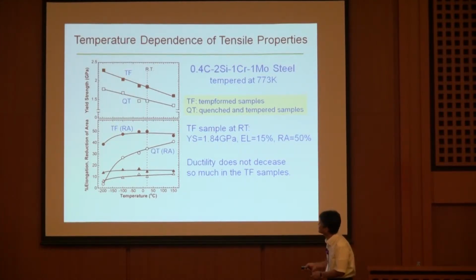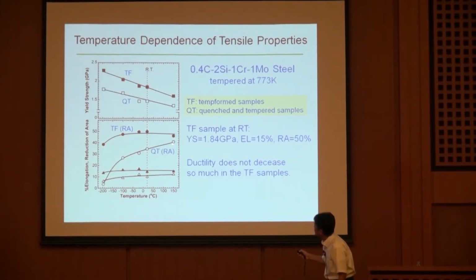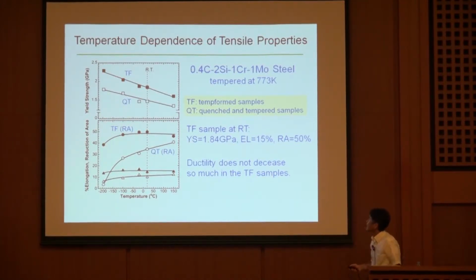For ductility, this is the total elongation. I'm sorry, this is the reduction in area. I'm sorry, this is the total elongation. The reduction in area of the QT sample, the conventional quench and tempered sample, decreases like this. It's like a ductile-brittle transition, but that degradation is not so significant for the temp-formed sample.